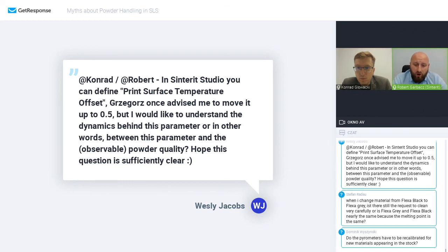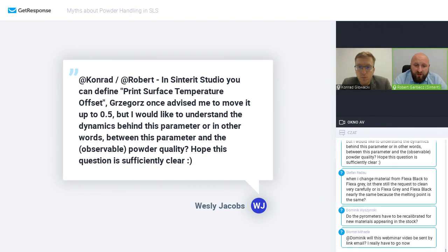So although we make this temperature stable, sometimes you need to cheat the temperature reading. For example, if you have 19 degrees in your office, or sometimes even 7 or 8 degrees, the temperature outside the printer is much lower than when the printer was calibrated. So sometimes you need to move it up to 0.5. Sometimes you need to move it down. It's very rare. That's why you should just contact Grzegorz.